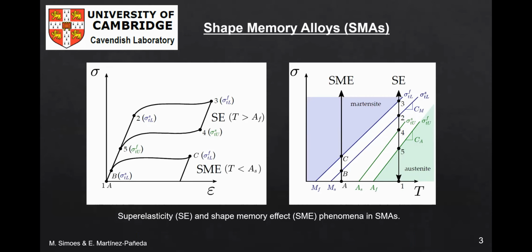So in shape memory alloys, where both superelasticity and shape memory effect can take place, their occurrence is governed by the temperature of the system, as shown in the figure at the right. This figure shows a typical shape memory alloy stress temperature curve, where MF and MS denote the martensite end and start temperatures, while AS and AF denote the austenite start and end temperatures.